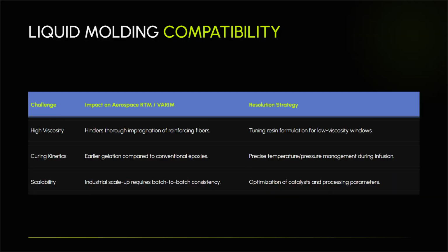Starting with liquid molding techniques like resin transfer molding and vacuum-assisted resin infusion molding. While Vitrimers are highly promising, integrating them into traditional aerospace manufacturing lines poses major processing difficulties. The first issue is high viscosity. The dynamic network structure often exhibits a higher intrinsic viscosity at standard processing temperatures, which severely hinders the thorough impregnation of reinforcing fiber beds, potentially leading to internal voids and structural defects.